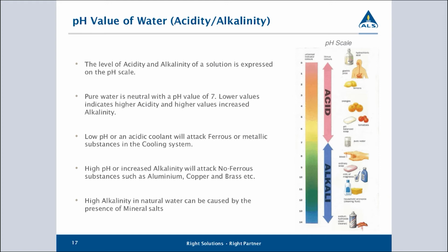If you see changes in pH, it's indicative of something happening to the system. That could be contamination or degradation of the coolant taking place, or a combination of those things. But as soon as we see shifts in the pH value, that starts as a very early warning indicator that this coolant is not working very well in this environment, and something is going wrong with this particular coolant.